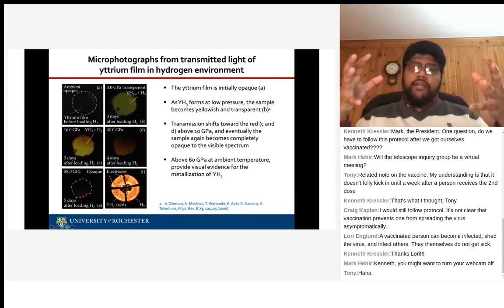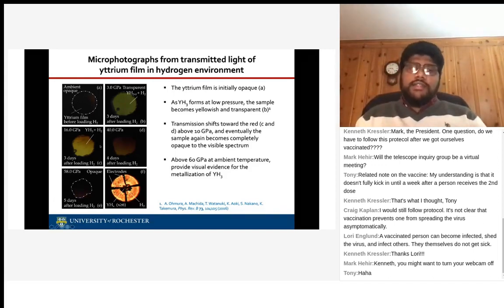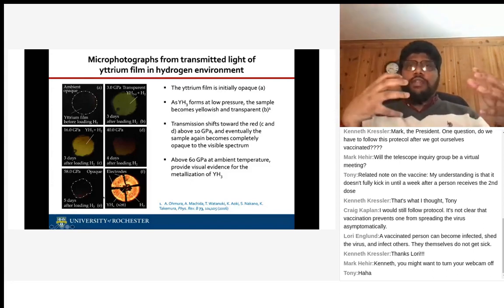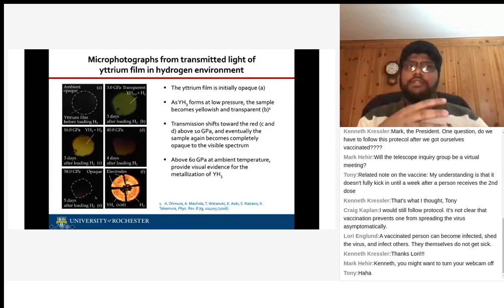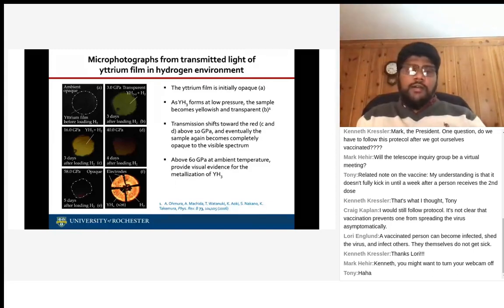And then if you take that yttrium hydride and squeeze it to higher pressures, you again see it become darker yellow, then sort of orange, then really orange and dark, and then really dark around 50 GPa, and then it becomes completely opaque. This means that visually you're seeing the evidence of it going from an insulator or semiconductor to a metal, because with a metal you can't see through, right? So you will see that transition. And this picture shows the four electrodes attached to this sample, with which you can measure the electrical resistance. This graph shows you how this process happened.